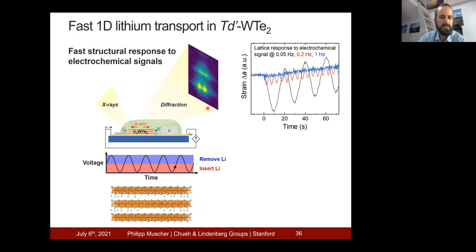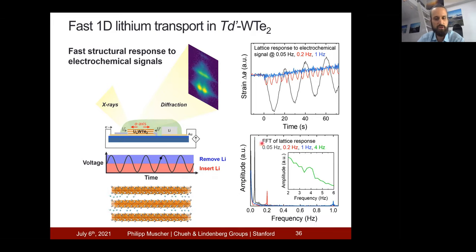From these diffraction patterns, we can of course deduce the structure of the material. Here I'm looking at the A-axis lattice parameter, and you can see if I have a 50 millihertz signal, the structure can follow, the lattice is following that signal. And the same can be said also for 1 hertz,